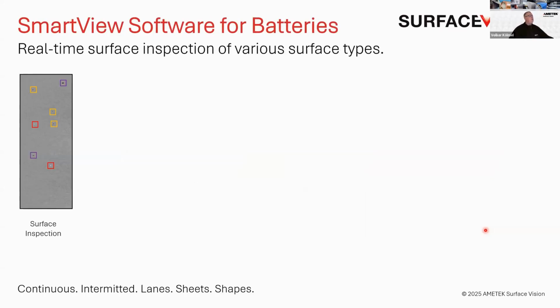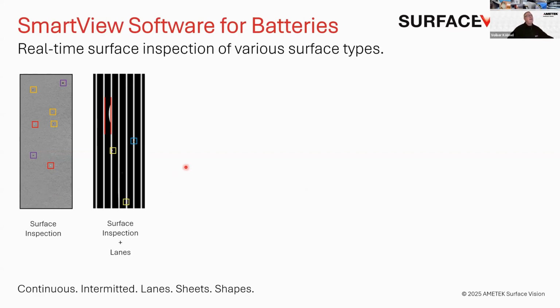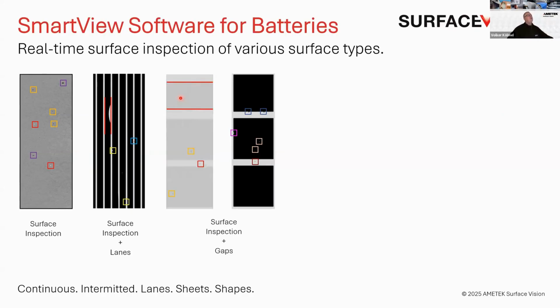When it comes to the surface itself, we have the inspection of a solid surface. So the software should be capable to inspect, for example, this, again, would be separator material. Then we have a surface which has a line structure in it, like the continuous coating, where you have the coated and substrate areas on top of it. So the software has to deal with this. Then, of course, you also have intermitted coated material. It's reduced demand, I have to say. So over the years, I think the continuous coating is a little bit leading, at least from the requests we get, but still here, it's a significant amount of coating we have to help.